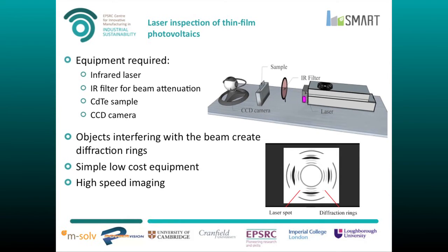So objects interfering with the beam create diffraction rings. So the laser spot is in the center, and then rings appear around the outside. Objects is defined as anything that gets between the beam and the camera. So that can be particles of dust in the air, it can be stray reflections from any surrounding equipment, and it can be flaws and pinholes in the cadmium telluride sample itself. So the equipment is fairly simple, it's fairly low cost, it's quite rapid. So the next question is, how do we isolate the cadmium telluride?